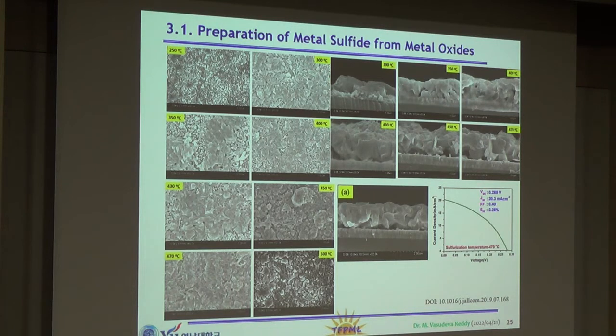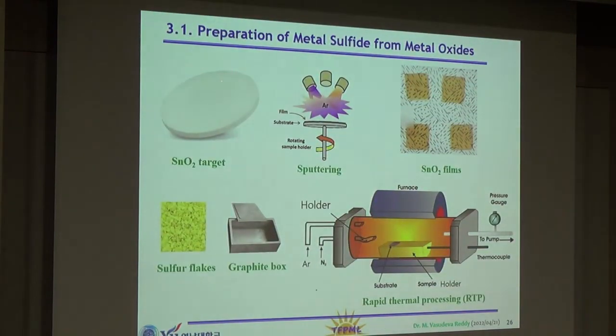also between the substrate and the film, there are some voids. Therefore, we realized maybe the oxide layers will provide the prominent path to reduce these surface problems, and also the voids, the gap between the substrate and the absorber layer. Therefore, we intended to sulfurize the tin oxide films in the sulfurization process. So this is the reason for developing this process. There are many pinholes in the samples, and also the surface is not uniform. Controlling the uniformity and the surface is harder in case of metal sulfurization. Therefore, we tried to deposit the metal oxide layers for sulfurization.